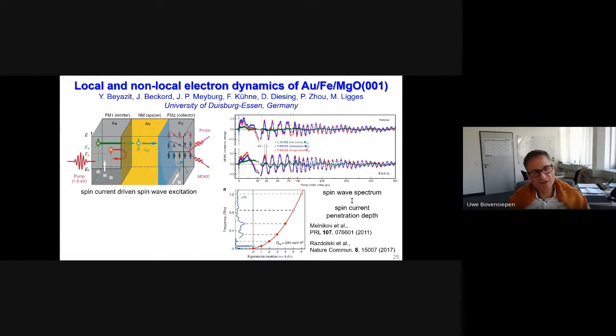And what we do there is using spin currents, so ultra-fast spin currents that we generate by absorbing femtosecond laser pulses in this iron constituent as an emitter. We inject this into gold, and then you have a spin current that impulsively generates spin waves at this second iron layer. The magnetization of those two layers are perpendicular to each other, and this we can probe by a magneto-optical Kerr effect, where we have the probing on the opposite side of the sample compared to the pumping.